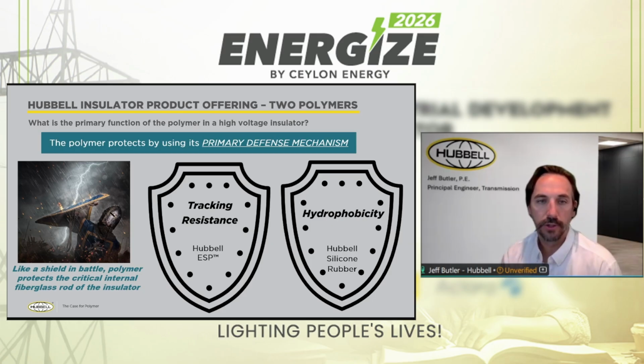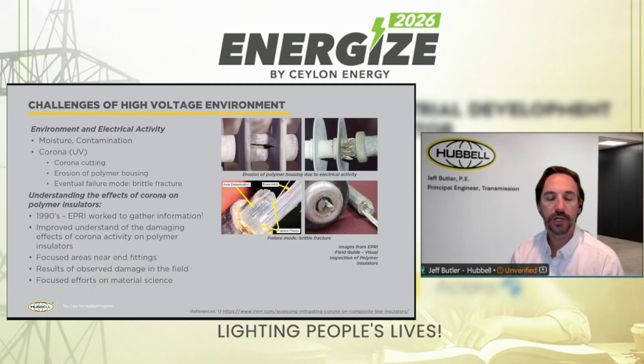So when we're looking at polymer insulators, it is understood that there are challenges faced in the electrical environment. There's moisture, there's contamination, there's corona activity, electrical activity, which creates UV. There's also UV from the sun, from solar exposure. All of that can lead to the phenomenon of corona cutting, erosion of the polymer housing, and an eventual failure mode referred to as brittle fracture. The picture in the bottom left shows brittle fracture, where you see fiberglass strands that have been cut clean. It almost looks like they were cut with a knife, and then the remaining strands lack the mechanical strength to maintain the mechanical load. As I mentioned, the primary function of an insulator is carrying that mechanical load.